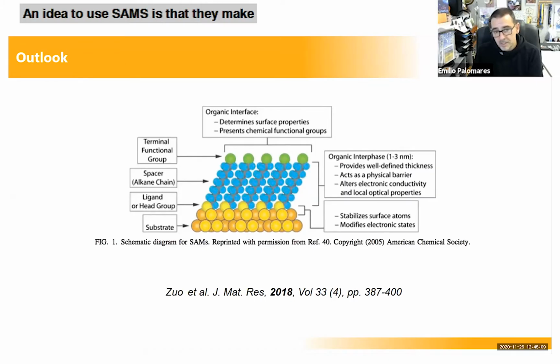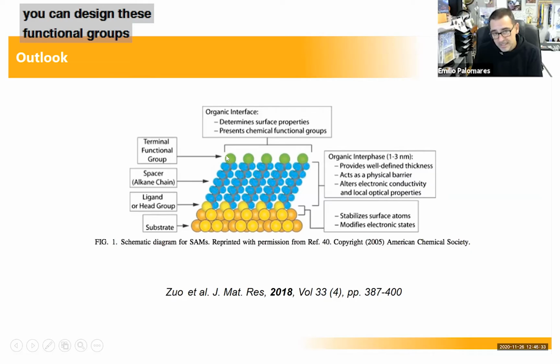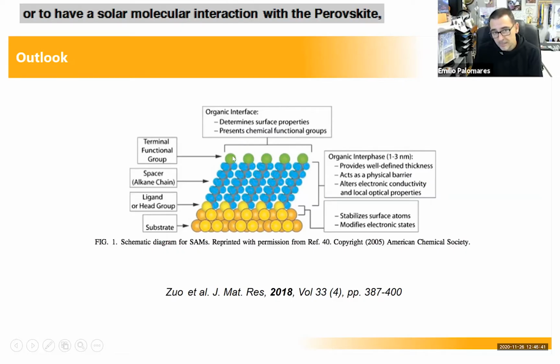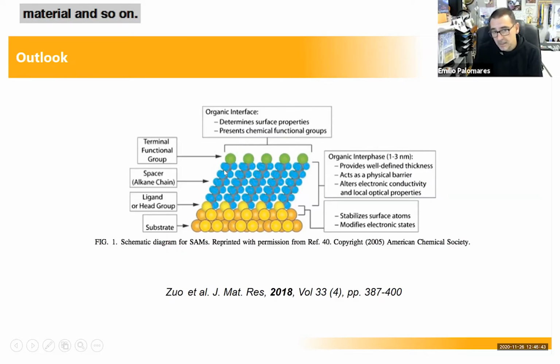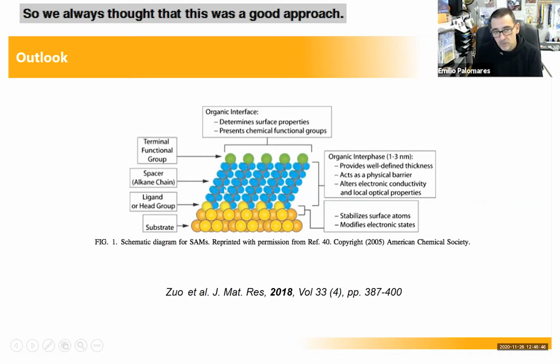And the idea to use SAMs is that they make a very good selective contact for devices, and I will show you some examples, not only for solar cells. Basically, you need a substrate, which usually is FTO or ITO, so fluorine-doped tin oxide or indium tin oxide. And then you have a spacer that usually is an alkane chain. And then you have functional groups. If you are clever enough, you can design these functional groups to change, for example, the work function of the substrate, or to have a supramolecular interaction with the perovskite material and so on. So we always thought that this was a good approach.